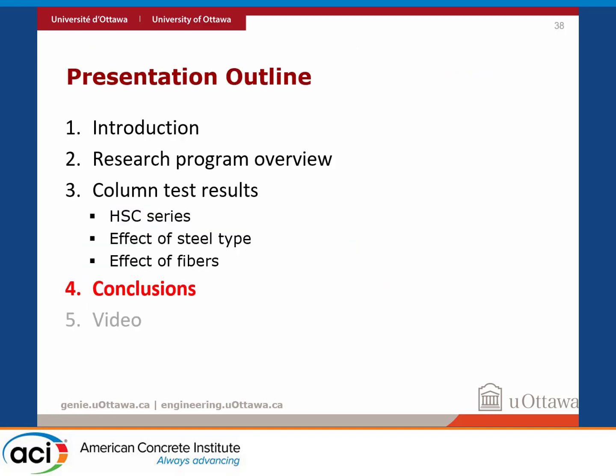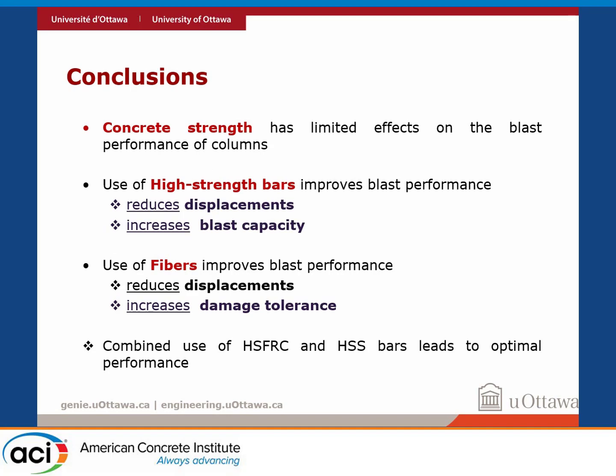In conclusions: concrete strength has limited effects on the blast performance of columns. High-strength bars significantly improve blast performance — they reduce maximum and residual displacement and increase blast capacity. The use of fibers also improves blast performance of HSC columns by reducing displacement; they don't increase blast capacity, but you get much better damage tolerance. And when you combine HSFRC with high-strength bars, you get optimal performance.